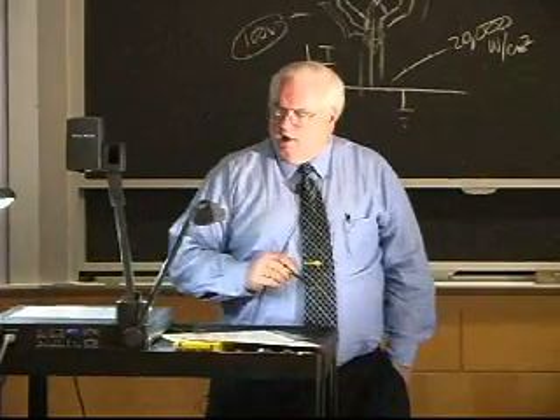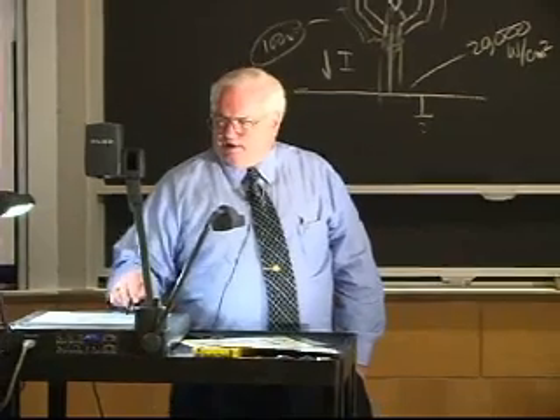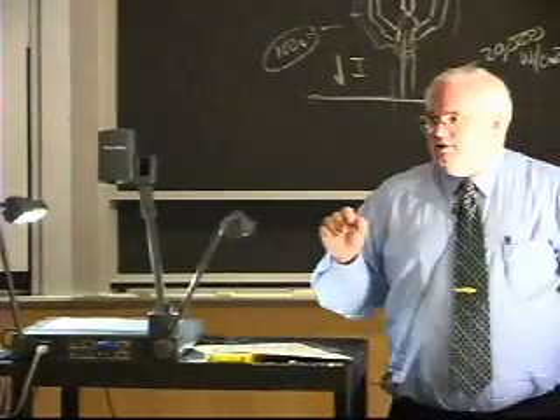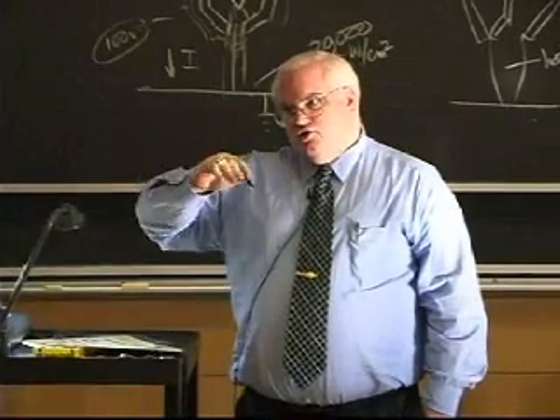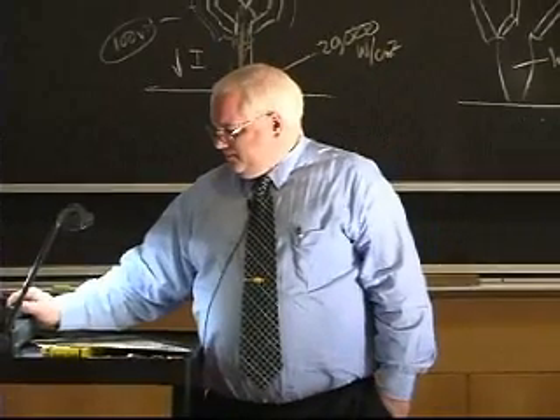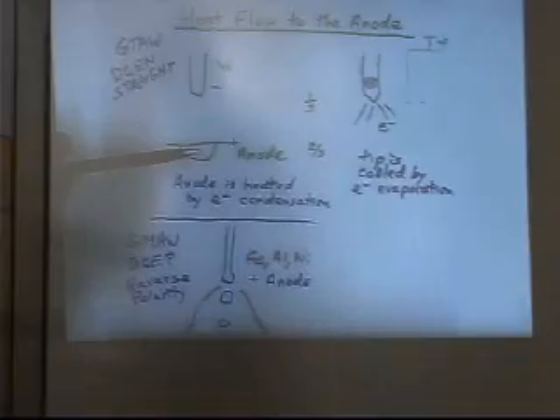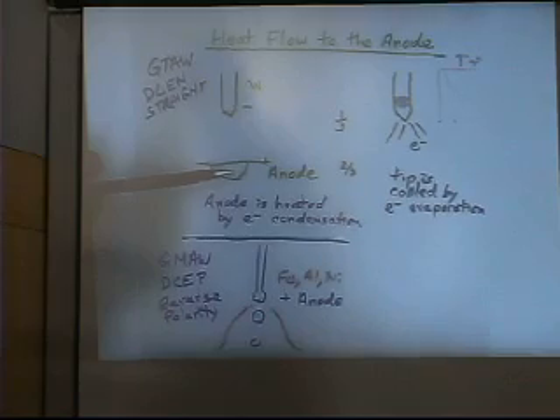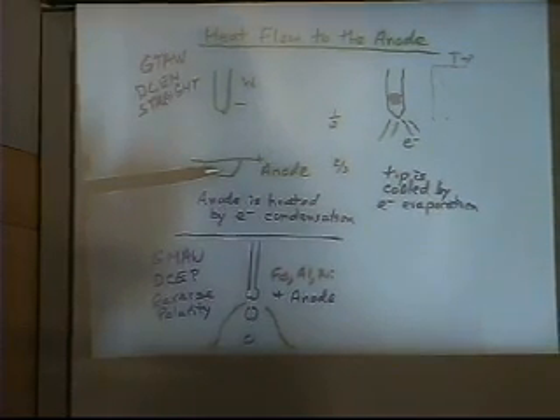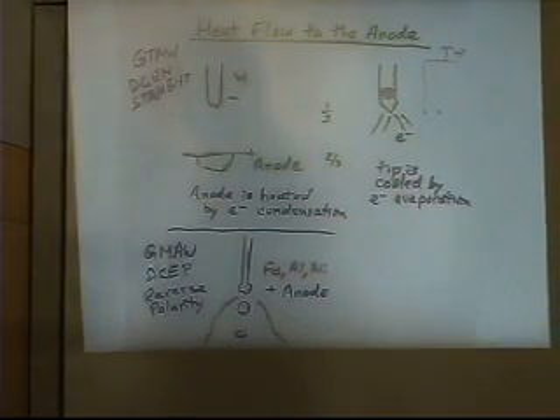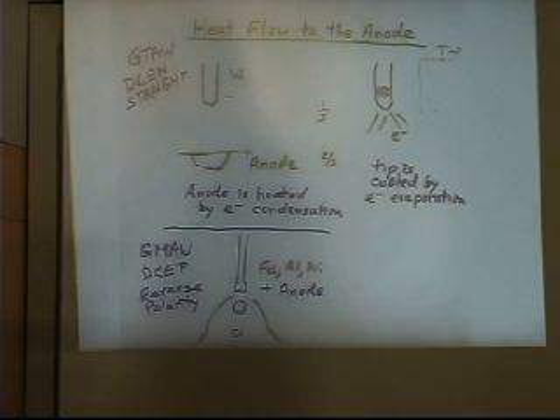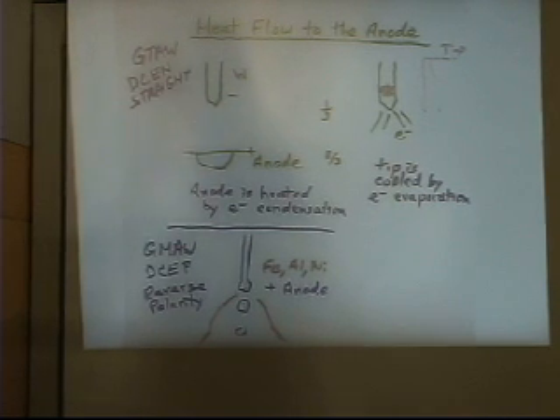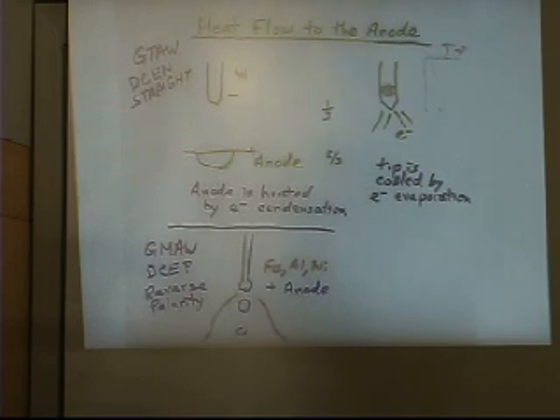So AC gas tungsten arc welding is commonly used for aluminum. However, because of this asymmetry of the electron flow between the cathode and the anode, if you just run straight AC, there is a rectifying action, and you'll get a little bit of DC offset, because the current that goes through when the aluminum is negative is not as high as the current that goes through when the aluminum is positive. So you get a slight offset rectification. It screws up your transformers. They like to have things balanced in terms of positive and negative cycles, in terms of magnetic fields and whatnot.